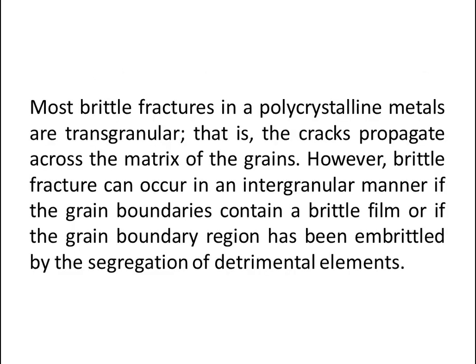Most brittle fractures in polycrystalline metals are transgranular — that is, the cracks propagate across the matrix of the grains. However, brittle fracture can occur in an intergranular manner if the grain boundaries contain a brittle film, or if the grain boundary region has been embrittled by the segregation of detrimental elements.